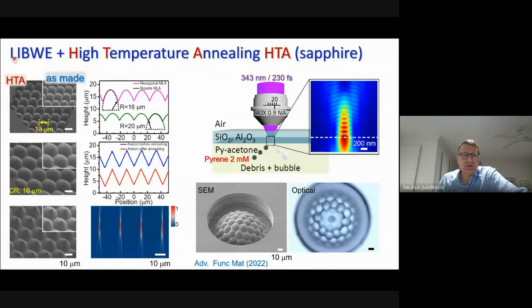One way to improve this is actually fabrication on the backside of your transparent substrate. LIBWE stands for light-induced backside wet etching. So this is exactly what is shown. You are shining femtosecond laser pulses onto the interface of the material which you want to fabricate and some one or two photon absorbing solution. We used acetone and pyrene dye.